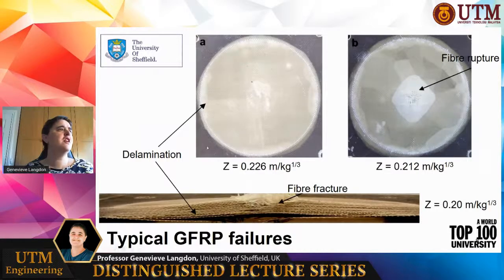So the dark areas around the outsides of those two figures A and B, which are at the top of the screen, are what the material would have looked like before it was blast loaded. And you can see that all of the part inside the circle has gone white. It's gone white because it's delaminated. So what's happened is that there's been a breaking of the bonds between the layers of the fibers, and that causes the whiteness that you can see on the screen.